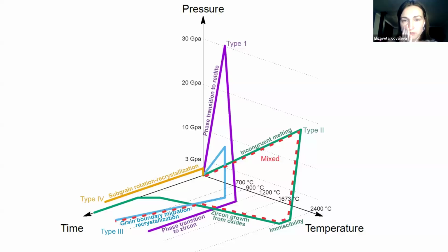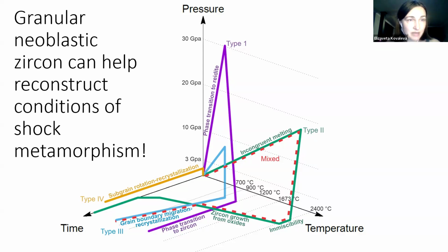And just a take-home message: every single one of these different types represents a different pressure, temperature, and time path. For example, type 1, you have a very high peak of pressure, and then pressure is released, and then you have a slight cooling, and then the reidite goes back to zircon. Type 2, you have smaller pressure but higher temperature, which is causing melting, and then recrystallization back again. So each of these shows a slightly different PT and time path.